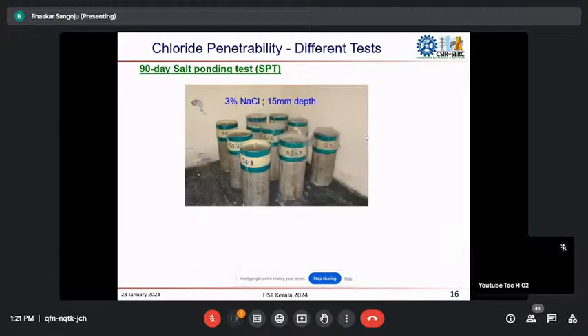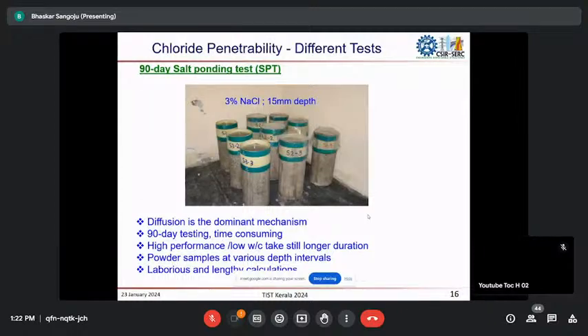And this is chloride. For evaluating chloride penetrability, there are different tests available. This is a 90-day salt ponding test. Here in this photograph you can see the cylinder, on one surface, say the top surface, we artificially created a pond. Then a NaCl solution, water with 3% concentration of NaCl, is poured, and 15 mm depth is maintained for a duration of, for example, 90 days or 60 days, or whatever it is.